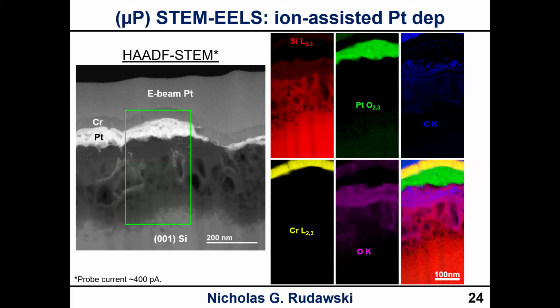This was with about 400 picoamps of current, so not quite as high as what we were using before. Generally speaking, you don't need as much current when you're doing EELS compared to EDS because the signal to noise in your maps tends to be better, which again could be a topic for another discussion at some point. But anyways, I wanted to show you an example of microprobe STEM EELS as well.